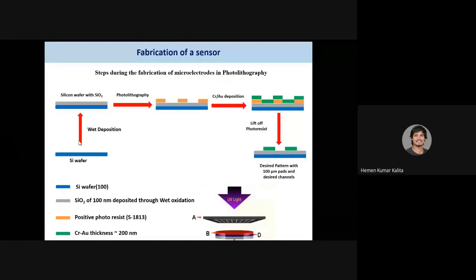In the first step, we take a silicon wafer. Here in this case, we have taken silicon wafer with 100 planes. After the silicon wafer is taken, we deposit silicon dioxide on the top of the silicon wafer. The process with which silicon dioxide is deposited is known as thermal deposition, wet deposition or dry deposition. Here we have taken wet deposition. Generally, wet deposition is used for larger thickness. For smaller thickness, dry deposition is used.